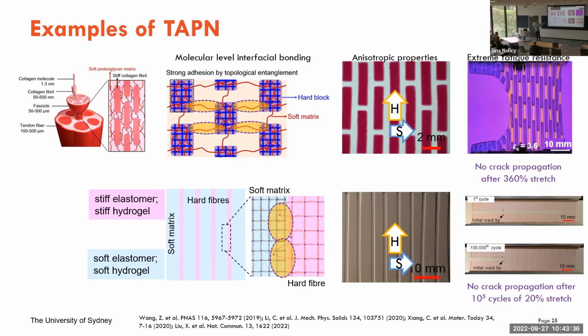At the bottom, we have some similar cases where there is a crack where you can see the crack tip. After 10 to the power of 5 cycles at 20% stretch, the crack actually doesn't propagate as well, because the whole body of material is involved in dissipating energy while those stiff materials are storing the elastic energy. So they actually can go back as well. They dissipate energy and return back to the same size that they used to be.